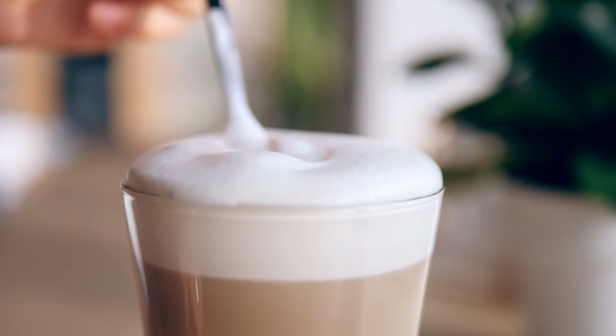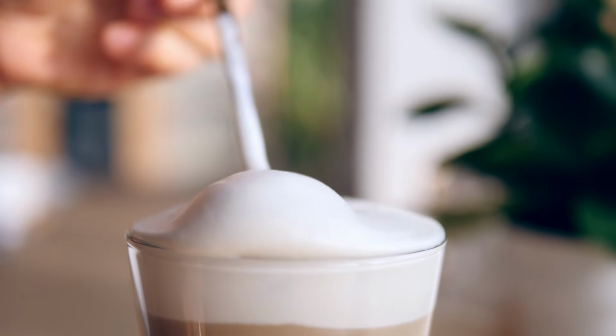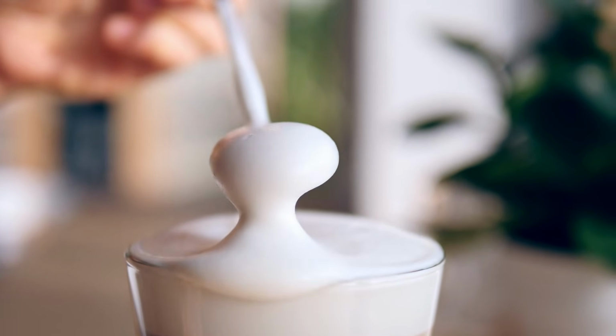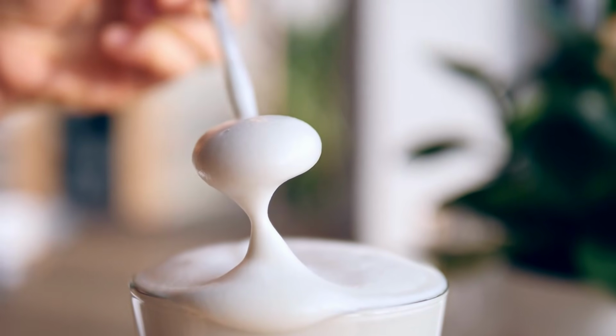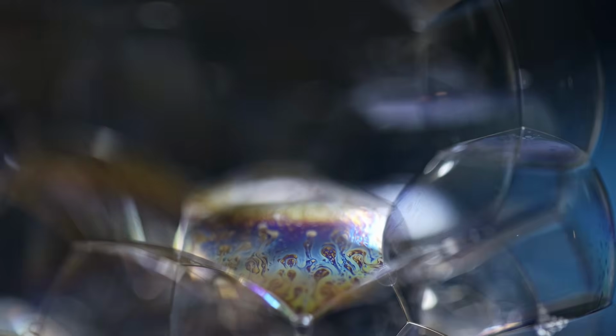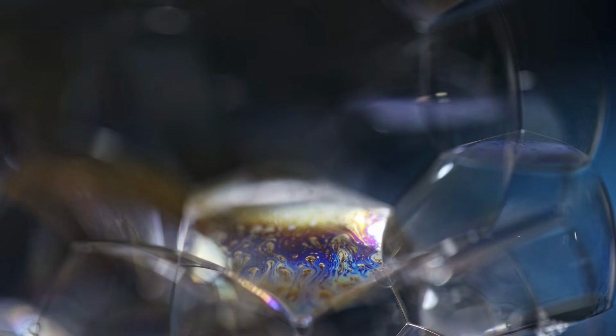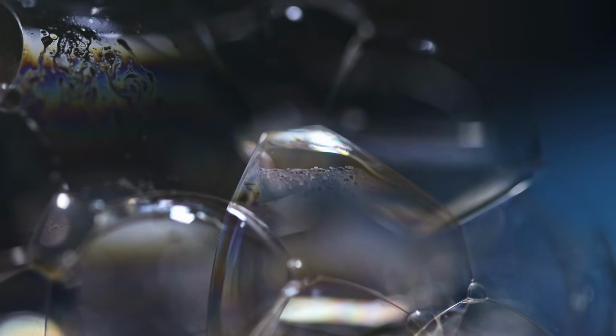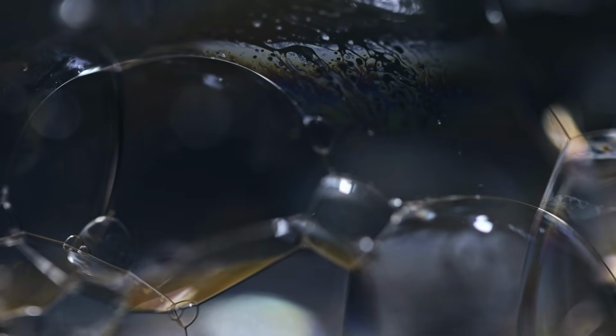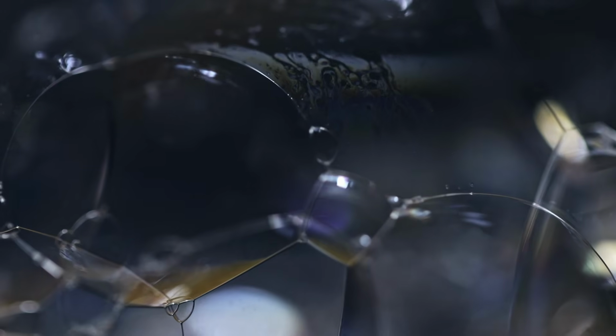When heated, these proteins break and the molecules unravel, reinforcing the bubble walls and stabilizing the foam. The increased viscosity slows down drainage and collapse, though if the viscosity becomes too high, the self-healing surface transport mechanism diminishes as the foam becomes more rigid. In a forming foam, bubbles with smaller radii have higher internal pressures. As the bubbles merge, larger bubbles grow by absorbing smaller ones because of this pressure difference. Gas from high-pressure bubbles tends to move to these bubbles with lower pressure. When surfactants are present, they pack closely to the bubble walls, reducing this gas movement. Typically, lighter surfactants are more effective at this because they can pack more tightly onto the surface.